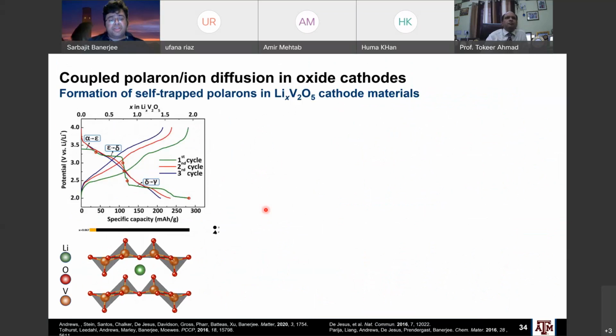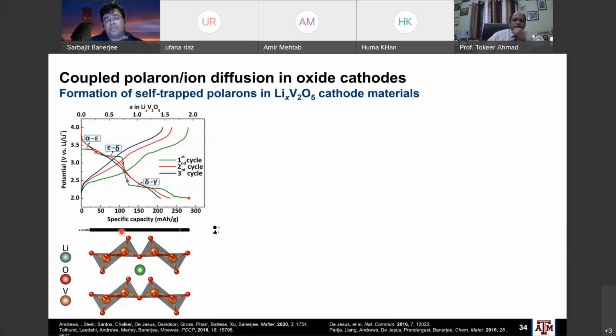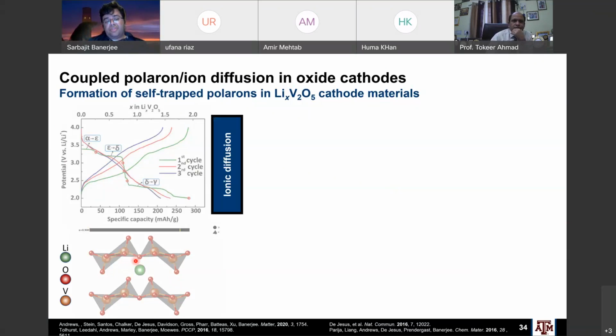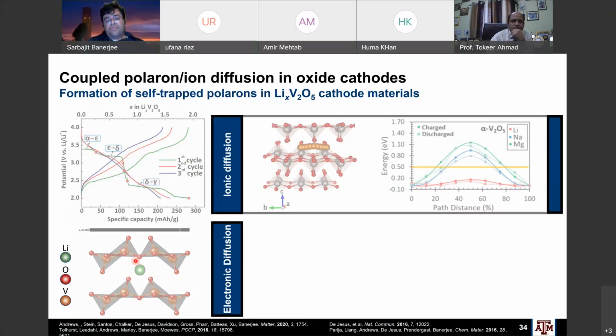Okay, so the message of the story, this is a discharge curve. The structure, because of these deficiencies that hold up lithium diffusion, means that there's a local buildup of lots of lithium ions because the ions are not moving freely, and that induces large concentration gradients, which induce this series of phase transformations. And these phase transformations then cause all sorts of other problems that I'm about to talk to you about. But fundamentally, what I want you to appreciate is that a lot of these problems are directly traceable to the basic atomistic chemistry of it.